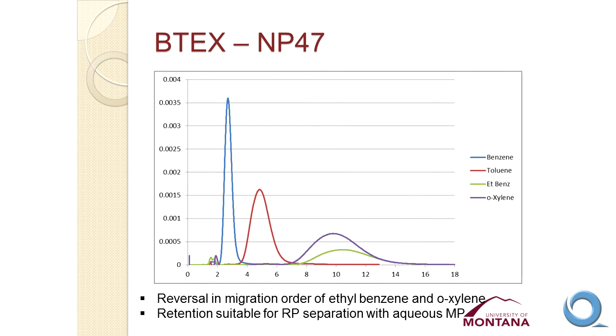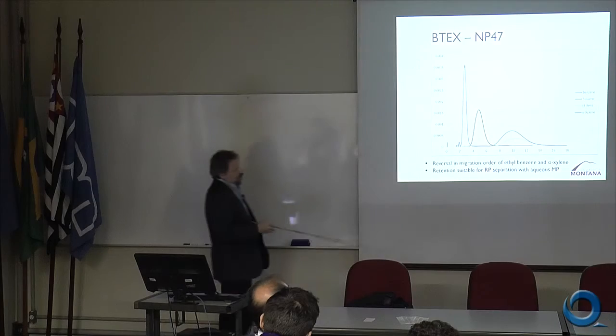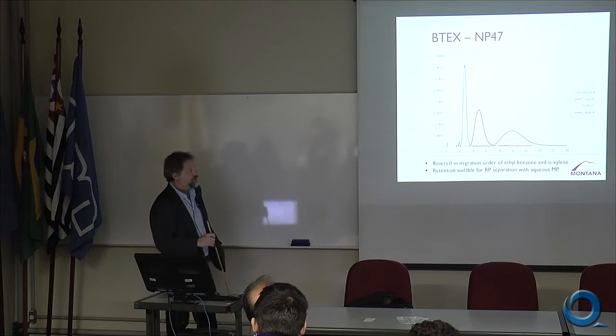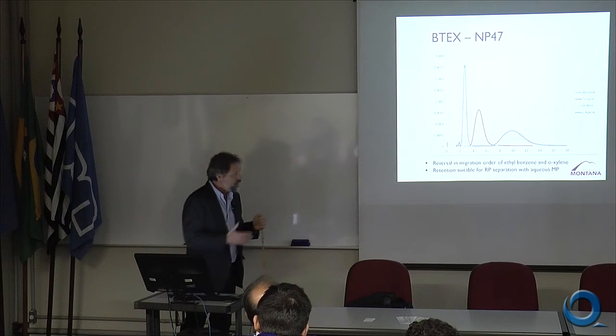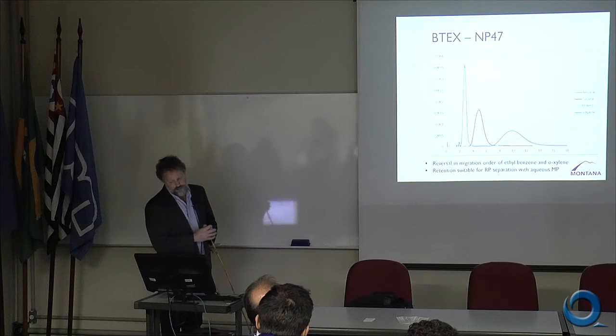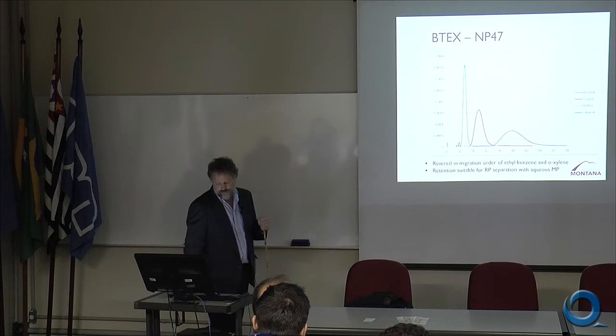One thing that was a little interesting is that if you look at the retention of benzene, toluene, xylene, and ethylbenzene, first of all, xylene and ethylbenzene were reversed on 47 relative to 32, so some strange, possibly interesting selectivity differences. But if you made a nice high-efficiency column with this system where you didn't have so much peak broadening, you could achieve a separation of these 4 compounds using just water as the mobile phase. So in column 32, you could do it even faster than you could with the material 47. So one potential application of these materials might be for that sort of an application where you would, instead of using high organic modified mobile phases, just use an aqueous mobile phase for the analysis of compounds like BTEX.